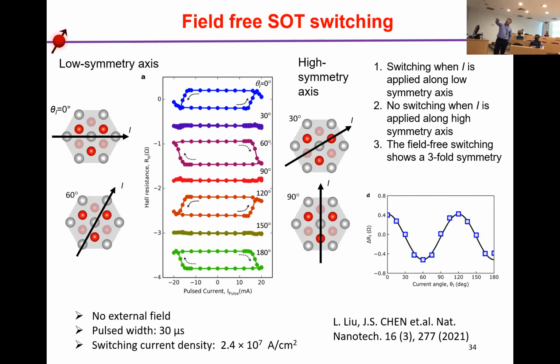Based on this, we have demonstrated that when the current is along the low symmetry axis, that means 0 degree, you can observe field-free switching. And in the high symmetry axis, no field-free switching. And in the other low symmetry axis, they reverse the directions, reversing the switching polarity.